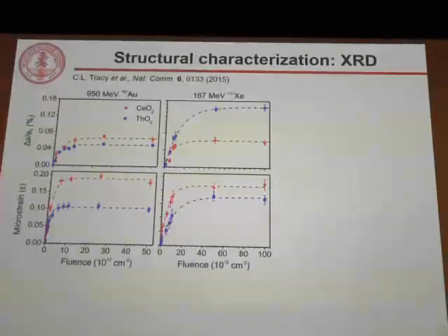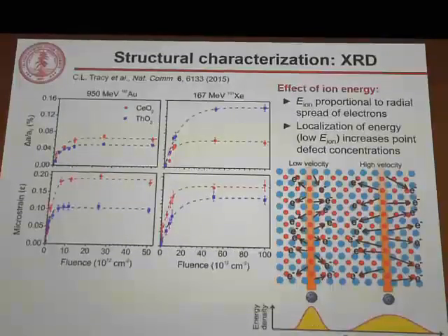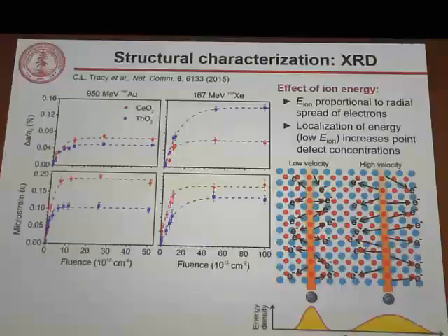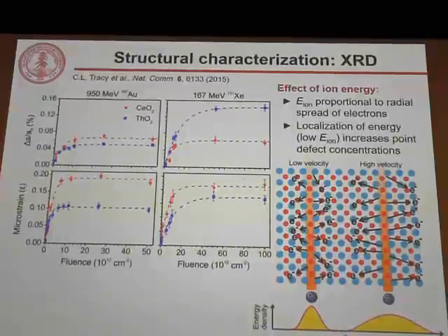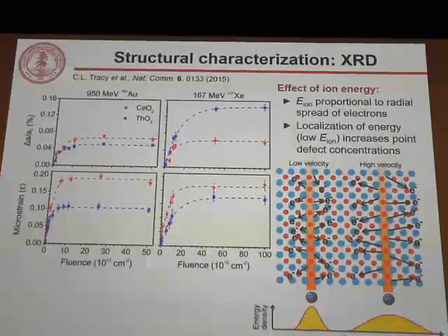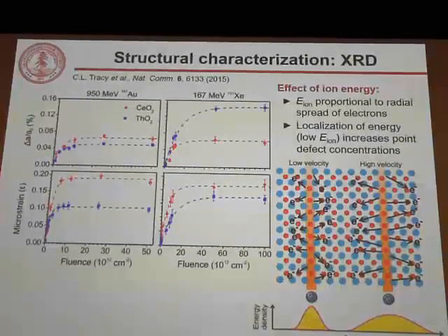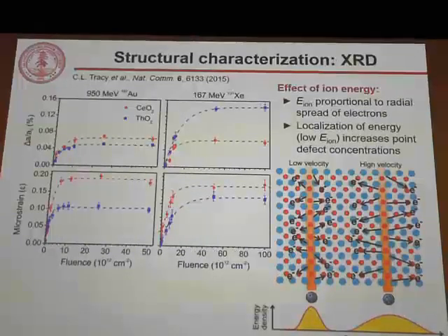Now the behavior of thorium dioxide makes a lot of sense here due to the known effect of ion energy on the damage induced. So we know that the ion energy is proportional to the radial spread of excited electrons. So I show that schematically here in the lower right. When we have a low energy, low velocity ion, electrons don't travel very far from the ion path before relaxing, meaning that the deposited energy is localized. If we increase the ion velocity or ion energy, as shown on the right side, these electrons travel a long distance before relaxing, so the energy that we deposit is very spread out.